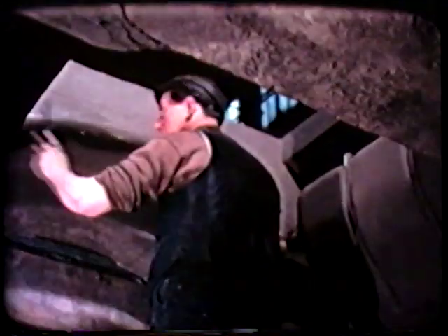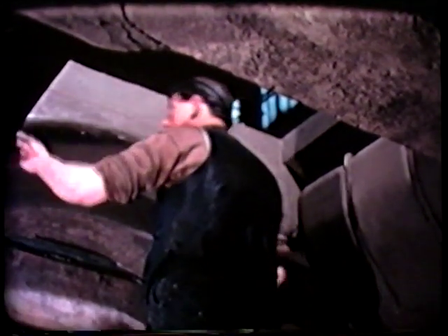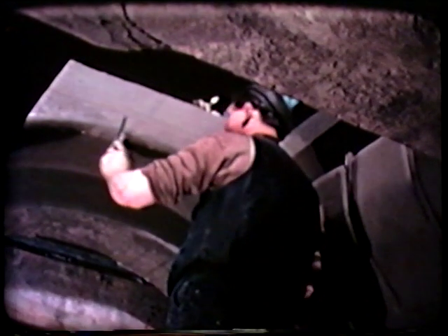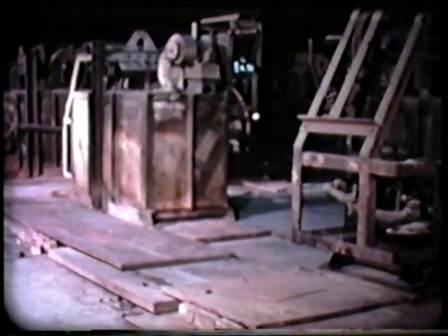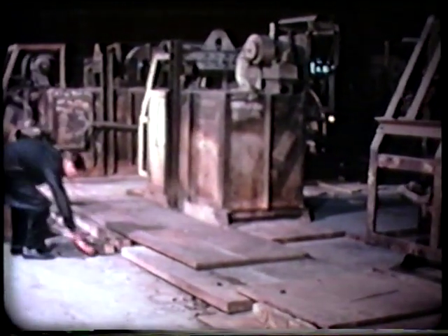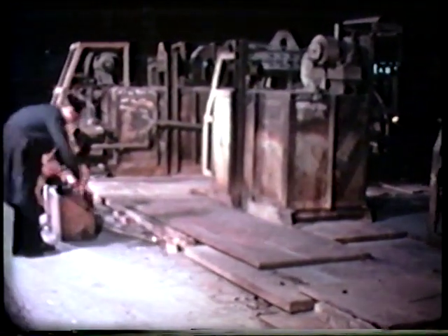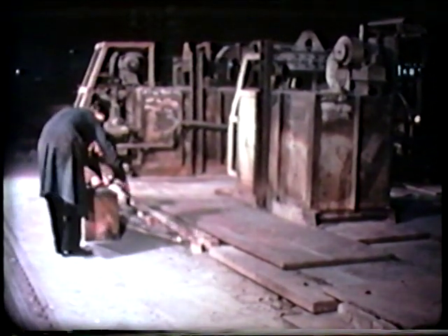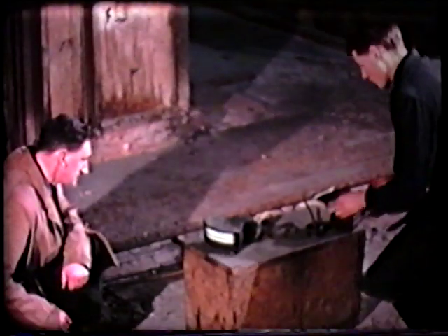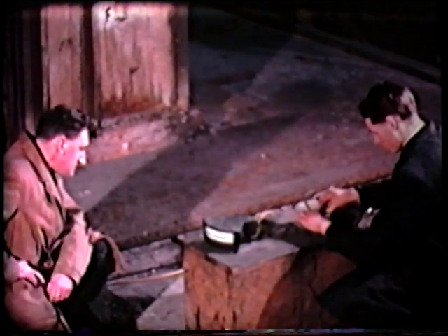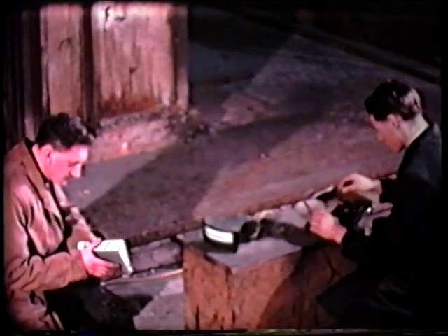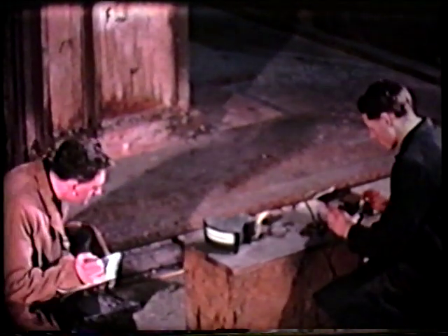The undersides of the top parts are treated in a similar manner and later finished with a coat of refractory paint. The mould is covered with plates for drying. Portable gas-fired heaters force air into the cavity for a period of 10 days. Readings are taken both of mould moisture content and temperature, the latter being gradually raised to 500 degrees centigrade.